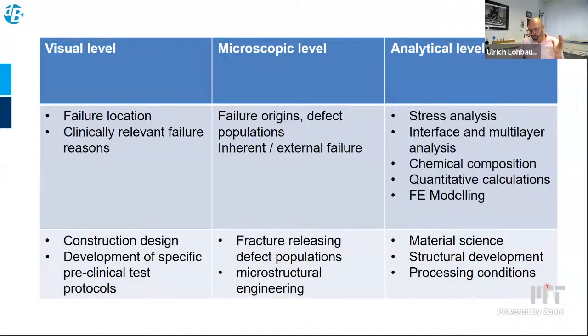assists our findings with modeling, stress analysis, especially for us in dentistry when we are working with bilayer or multi-layer structures. Think of a crown that has a strong zirconia core that is veneered with a weaker porcelain material. We can also analyze the chemical composition to see heterogeneities in the material, and make quantitative calculations through the fracture toughness. FE modeling, everything's possible. So the question is always what you wish to use fractography for. At some point, it's enough to use the visual level to see the failure reasons, to identify the clinical failure reasons.